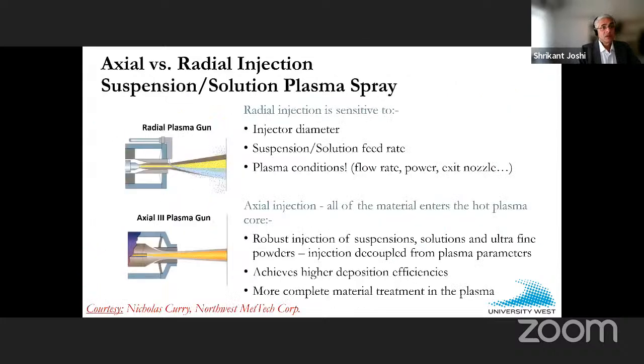And the reason for that is when you use radial injection, the injection of the liquid feedstock is very sensitive to the injector diameter. It always is sensitive to the feed rate, particularly so when you inject it radially. And then, you do not utilize all the energy that is available in a plasma plume. And considering the fact that the liquid feedstock per se needs more energy, we were destined to have problems with radial injection.